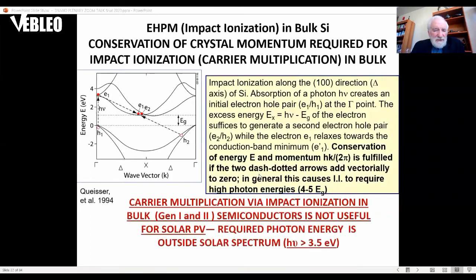But when it's produced in bulk semiconductors, you have to satisfy momentum conservation. In the bulk material, you don't have the quantization, of course, and you've got a continuum, and you can describe it by this band structure. The transition of the hole from the bottom of the conduction band to excite a second electron-hole pair requires that the momentum is canceled. And I didn't show the second transition here, but there's a second process where this energy of the hole going from here to here just excites another electron across the band gap.